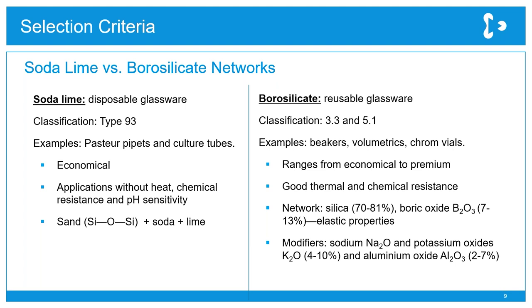Borosilicate glass is more commonly used for lab glassware. And this was originally invented by Otto Schott around 150 years ago. There are two types, 3.3 and 5.1. And it's used to make a range of products from beakers to volumetrics to chromatography vials. The big advantage of borosilicate is that it's got excellent thermal and chemical resistant properties. So it works really well in the lab, especially when we're heating glassware, using solvents and such. And in contrast to soda lime, borosilicate contains boric oxide, which gives it its elastic properties.